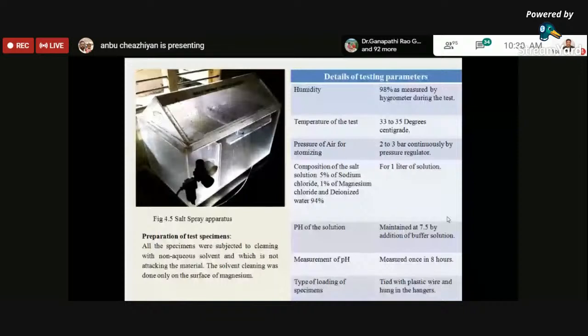So these were the testing parameters that we have maintained for corrosion resistance. That is 98% humidity measured by hygrometer during the test, and the temperature of the test is maintained at 30 to 35 degrees centigrade, with air pressure applied. We applied a salt solution of 5% sodium chloride and 1% magnesium chloride in deionized water for 1 liter of solution. Every few minutes it will spray automatically through the sprayer. Also, all the specimens were cleaned with a non-aqueous solvent, which does not attack the materials. The solvent cleaning was done only on the surface of the, sorry, it's magnesium, I told.